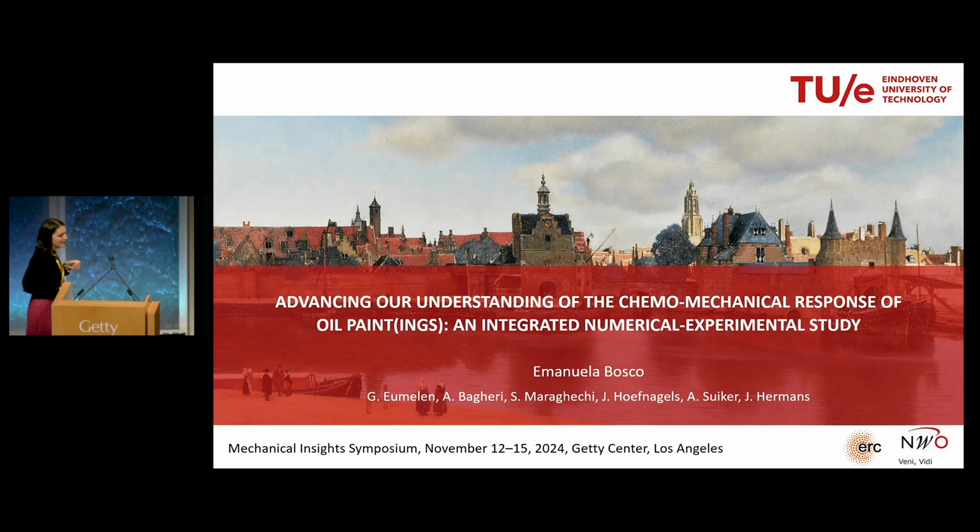Yeah, so I looked a bit in the literature and I thought we could use focused ion beam milling. It's not sure that it will work because it should be done in vacuum, so it could maybe damage the paint. I'm not talking about this one; this one we are manually cutting with blades. But I've seen that other people have used this for polymers, so there is hope that we can also adopt this for preparing paint samples.